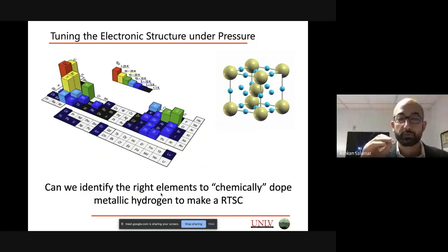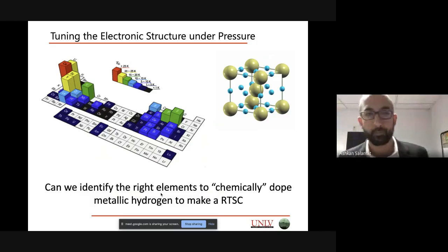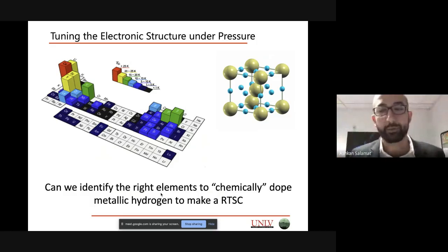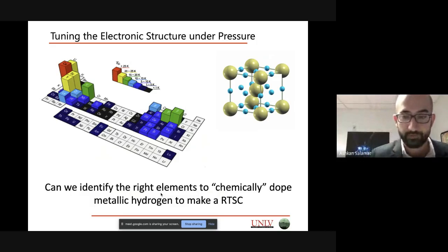So we want to dope metallic hydrogen. We know it's a high temperature superconductor. We want to dope it. In fact, we even had a helping hand. It was even made easier for us. We knew hydrogen sulfide was already a high TC superconductor. So the name of the game was to find a sweet spot between hydrogen sulfide and hydrogen where we could dope the system in such a way to achieve RTSC, room temperature superconductivity.